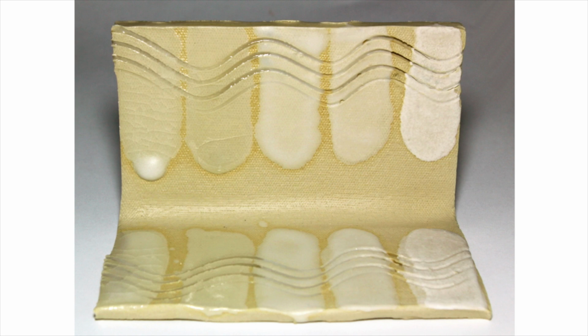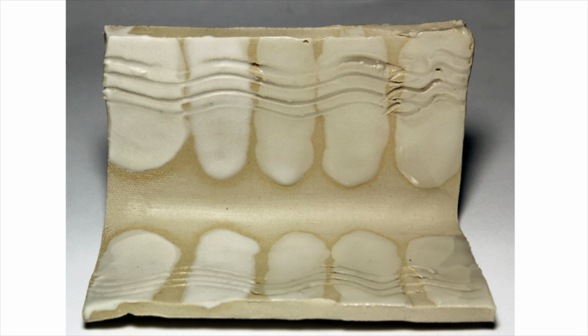Or take out the silica content—so I'm showing several different ways—and add it back into the glaze. I like the soft satin quality created by the second stripe with a 10% addition of silica to the glaze, so I made up that for this bottle.